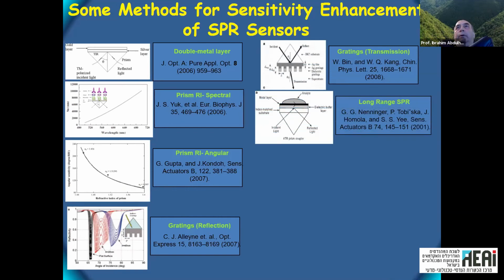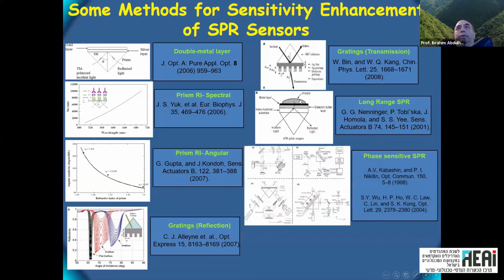And then there's the long range SPR, where you have two plasmons, one on the bottom of the metal layer and one on the top. So the bottom one can be used as a reference, and the top one has slightly larger penetration depth. That's why it propagates a longer distance also, because there is less field in the metal, so it gets absorbed less, it can propagate a longer distance. It has the advantage of being a self-reference sensor.